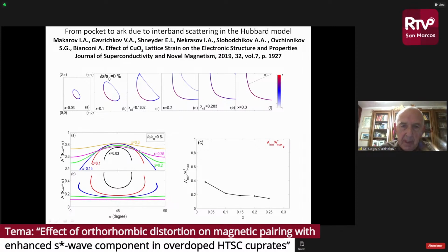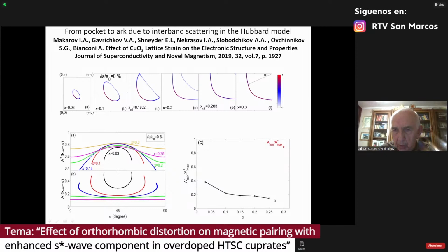The idea of the pseudogap is demonstrated below. For example, we have two surfaces with a minimal spectral weight and the maximal spectral weight. And on the right lower picture, we show the ratio of minimal spectral weight to the maximal spectral weight. We can see that it decreases with doping, and finally it goes to zero. So there is no small Fermi surface pocket. Only the normal Fermi liquid surface survives in the large doping.